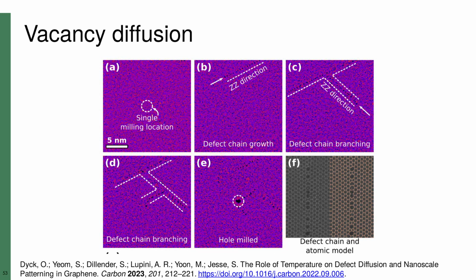If we zoom in and look more carefully at the structure of these chains, we find that they are primarily structured like a stack of reconstructed di-vacancies. We are indeed creating many vacancies while trying to mill, but these vacancies diffuse away from the milling location so fast that we cannot even see them.